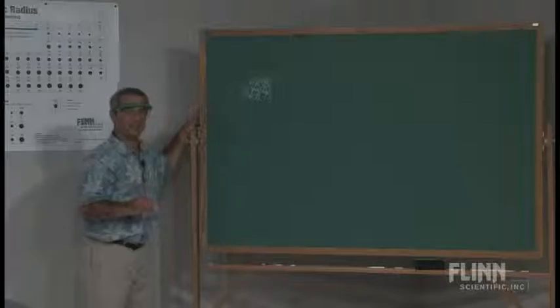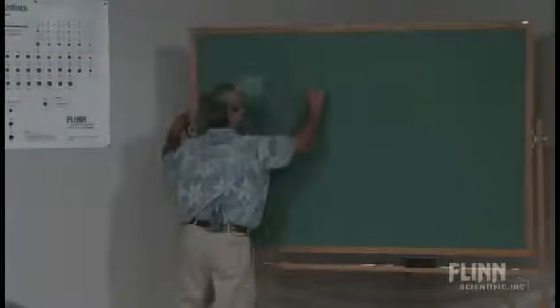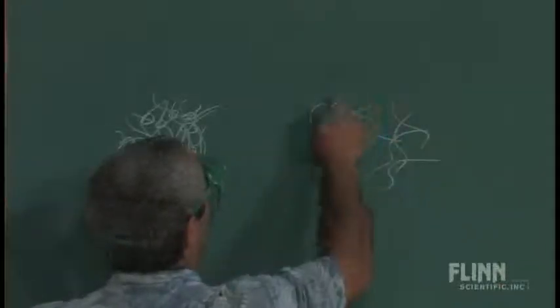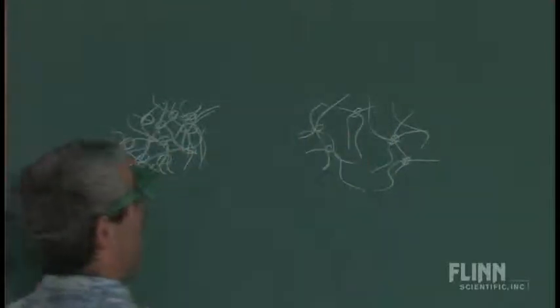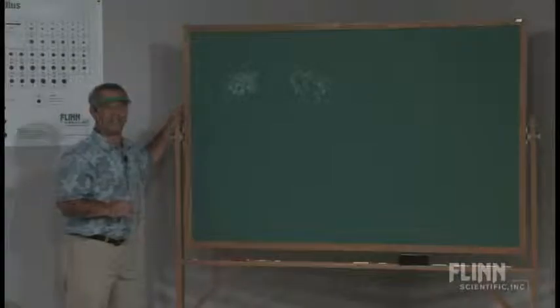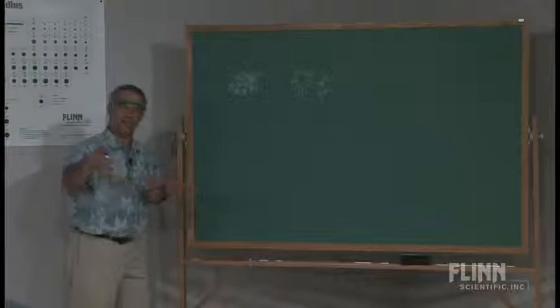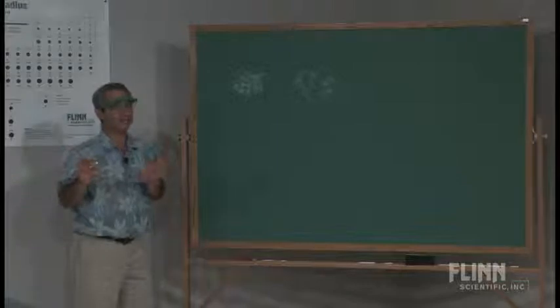So you can fine-tune the viscosity by adding water. So again, that would take those short polymer chains and spread them out some more. And now when you go ahead and add the borate, you don't get nearly as much cross-linking. You do get some, of course. That's what causes the increase in viscosity. But the fact that the polymer chains are spread out a bit first and then cross-linked is what gives you that just the right consistency. So that glue to water proportion, about 50-50, is critical.